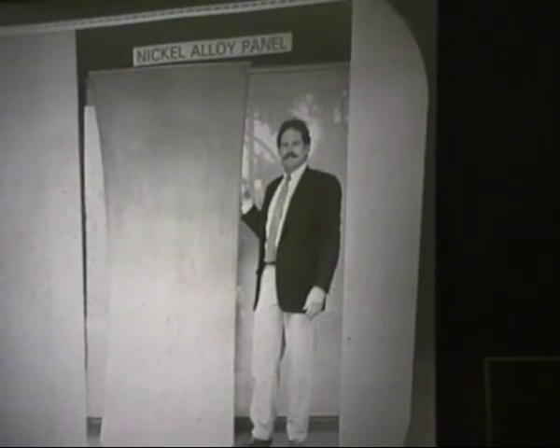And the other thing that was important about it, the skins on this panel are 8 thousandths of an inch thick. And there was a question of how tight a tolerance you could keep on the skin gauge, because if you're off by a couple of thousandths, that's 25% of the gauge. So it's either 25% too weak, or 25% too heavy, depending on whether it's plus or minus. And so the result was that in this particular panel, the tolerance on the skin gauge is held within 0.6 of a thousandth of an inch.